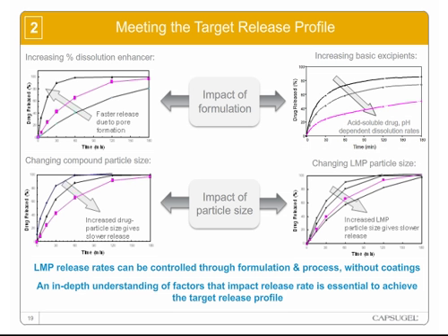This slide speaks to some additional in vitro work that was carried out to systematically evaluate the effect of various LMP formulation variables on the azithromycin release profile. In the upper two panels, the results clearly show that drug release rate can be modified by changing the level of only one formulation component, either the level of dissolution enhancer in the LMP formulation itself, as shown in the upper left, or the level of basic excipient in the final suspension formulation, as shown on the upper right panel.